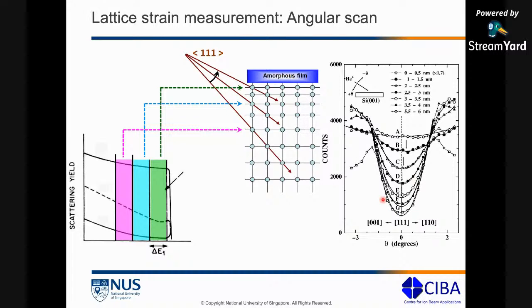And then each of the points on these curves correspond to the tilt degrees that we gave, right? So we started from the channeled orientation, which was the 0 degrees. Then we went plus 0.2, we collect a spectrum. We went plus 0.4, we collect a spectrum. Then we come back to minus 0.2, we collect a spectrum. Minus 0.4, we collect a spectrum, right? So there are 5 of these spectra that were collected. And when we put all of this together, these are the set of curves that we get.